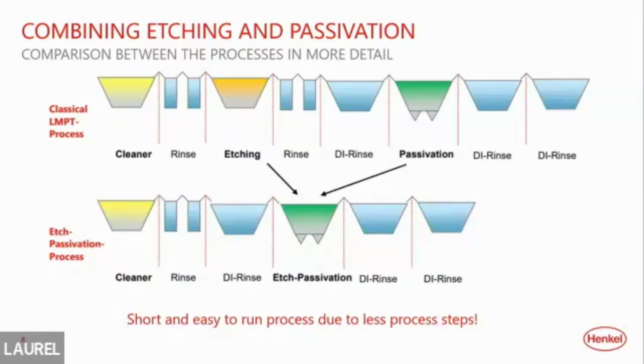And we use that DI water there because we don't want to drag any additional contaminants into our passivation stage, because honestly, that passivation stage is built up at maybe 1.5%, 2% chemistry. So you don't want to drag any contaminants into it. Just keep it as clean as possible. It'll last you as long as possible. And when I say DI rinse, just like David said, DI or RO water. And then we follow it up with a couple of good rinses and then force air dry it and send it on its way.